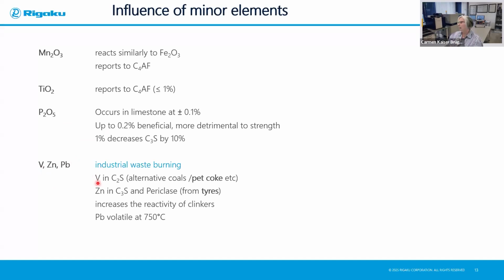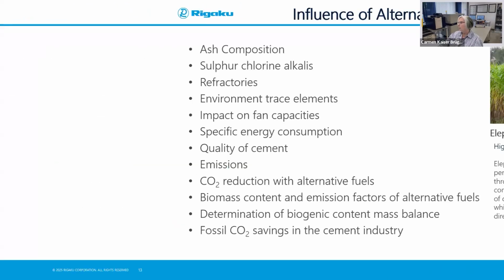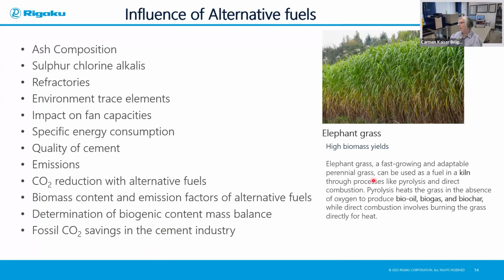For example, vanadium can influence the C2S. The vanadium can come from pet coke, for example, or any alternative coals that we use. If we're burning tires, for example, the tires contain a lot of zinc. And of course, the zinc can influence the C3S content. So these will increase the reactivity of the clinker. And lead, of course, is very volatile at 750 degrees and will also influence the reactivity of the clinker. So we need to really quantify the analytics of the alternative fuels. If you look at the alternative fuels, here we have a nice example of elephant grass. This has a very high biomass and can yield a lot of energy for the process.